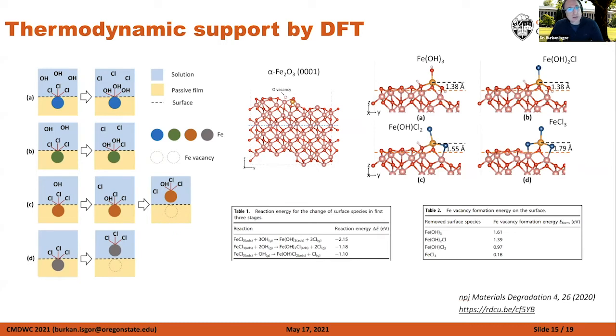And DFT is very good at answering these kinds of questions. You can look at different things like, for example, reaction energies. A negative reaction energy means that the process is feasible. You can look at the bond lengths. The longer the bond length means the system is stretched longer. You can look at iron vacancy formation energies. You can see the lower the energy, the more tendency for iron vacancies to form.